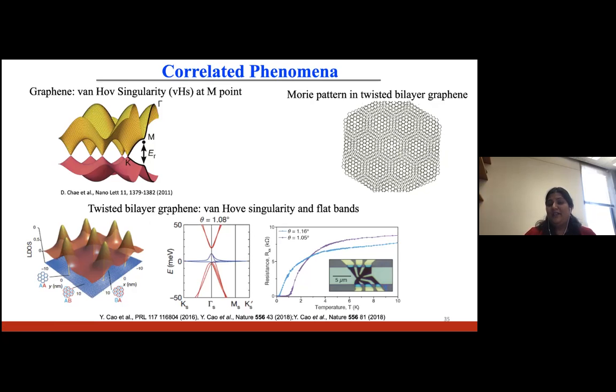And so we saw that if we stack two graphene layers and rotate them, these two Dirac cones hybridize and form the superlattice Van Hove singularities, with an energy that can decrease as the twist angle between them decreases. And so in twisted bilayer graphene, we've seen that at a magic angle, we can get superconductivity. So, interesting correlated phenomena.